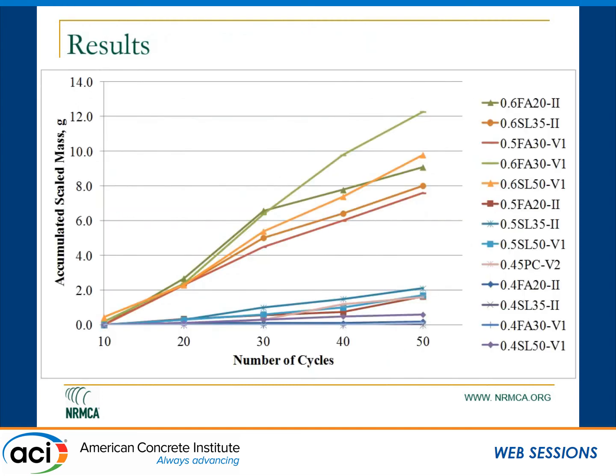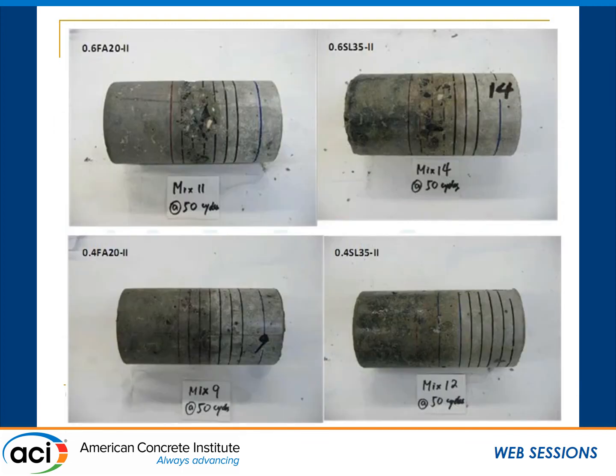The accumulated scale mass data looks pretty good. The high water-cement ratio mixes are all accumulating very high scaling mass, measured every 10 cycles. Then the 0.5 water-cement ratio mixes, and then the 0.4 mixes. One 0.5 fly ash 20 mixture came up a little high. Interestingly, the slag-50 mixture that had shown high scaling in the previous long-term test didn't show up here — it had low accumulated scaling mass. Looking at the prism images, the 0.6 fly ash-20 is clearly more scaled than the 0.4 fly ash-20, and slag-35 follows the same trend.